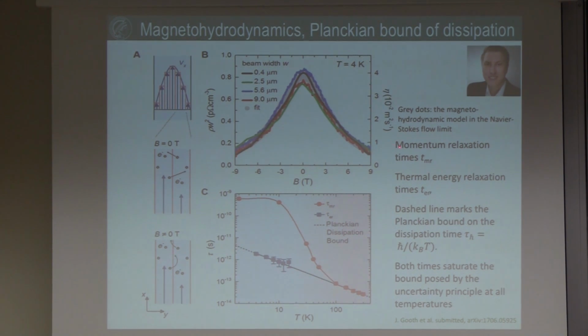So he simply looked up what is the magnetohydrodynamic model. This was developed for plasma physics, for high energy physics, and it gives you - we did the rho width squared versus the magnetic field for different widths of the crystals, and they all lie together on one line, easily fittable with this magnetohydrodynamic model, which originally was made for plasma.